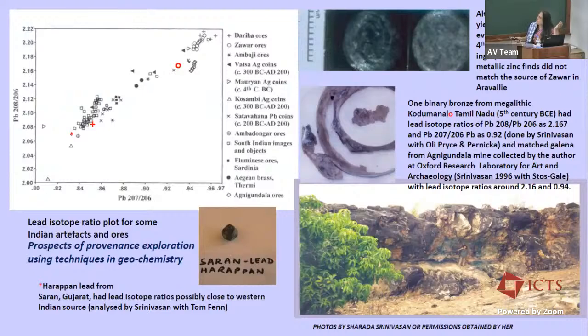If you have found the lead isotope ratios of a particular ore source, it could match with a particular artifact. And we have an interesting example here of Harappan leads from Saran, which I analyzed along with Dr. Tom Fenn. And these are some of the South Indian bronzes I've analyzed, which I'll talk more about tomorrow. We do see that Saran has some match with some early analysis from Western India, Ambadongar, though I don't quite know where that exactly is. There needs to be some more work done there, but I know it's somewhere in Western India, and that seems quite plausible because this is from the Gujarat region.